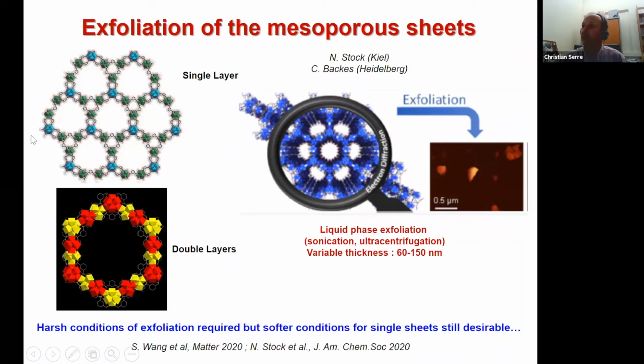Because this is a single layer of the mesoporous MOF, and as you can see on the bottom left, this is a double layer, and these layers nicely pack. So this is unfortunate, because they could pack in the center, and then you will have a much lower porosity. And they tried, in collaboration with a group in Heidelberg, to exfoliate by liquid phase exfoliation using different parameters, sonication, ultracentrifugation. And they could not yet get to nanosheets. They could only get to 60 to 150 nanometer thickness, as a proof of concept that this material could be at least exfoliated, the same as clays.